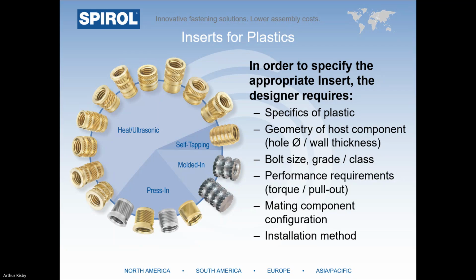In order to specify the best insert for a particular application, it is critical to understand the plastic specifics, meaning not just whether it is thermoplastic or thermoset, but what specific type of plastic it is, the percentage of fill, and the type of fill. If possible, the brand name of plastic, such as a DuPont Nylon 66 with 30% glass fill. We also need to understand the geometry of the host component, including available space for hole diameter and wall thickness, what bolt size you're planning on using, and what's the grade or class of bolt you're going to be using. This is very important because, as I mentioned earlier, the class or grade actually dictates what the recommended tightening torque is for that bolt size.